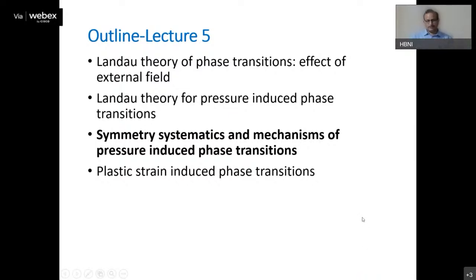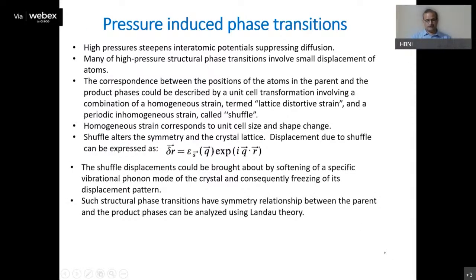Now let me come to the symmetry systematics and the mechanisms of pressure-induced phase transitions. As I discussed in the earlier talk, high pressure basically suppresses diffusion, because the interatomic potentials steepen when you apply high pressures. And so phase transitions basically take place by a very small movement of the atoms. Many times there is a symmetry relationship between the initial and daughter phase. So what kind of distortions, what kind of displacement can we describe?